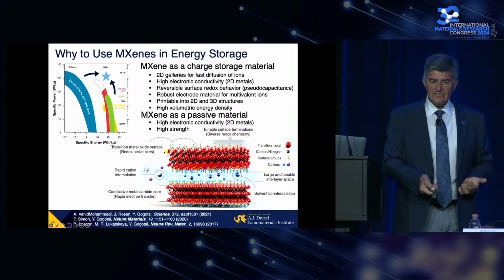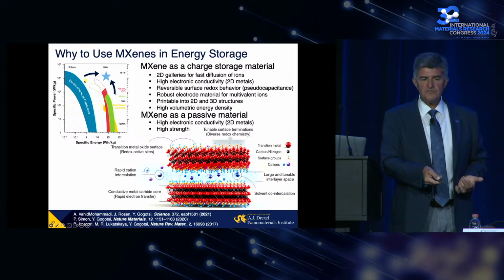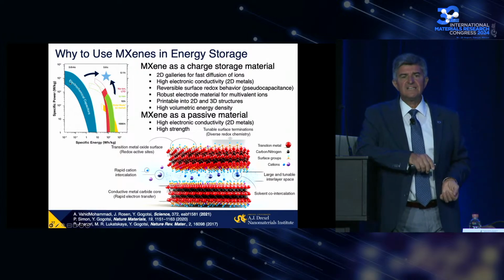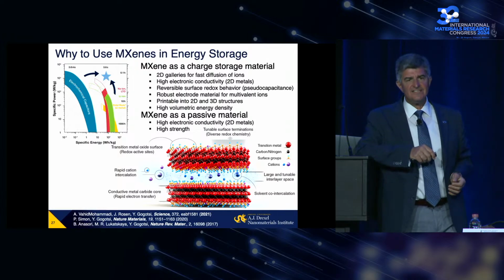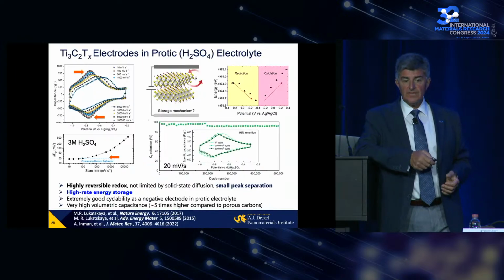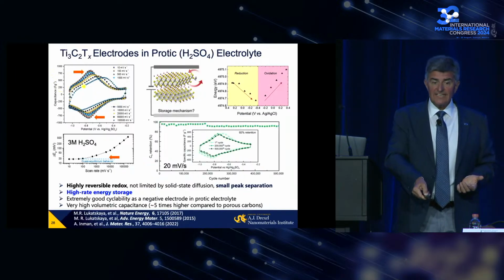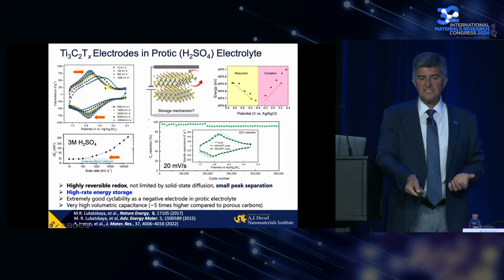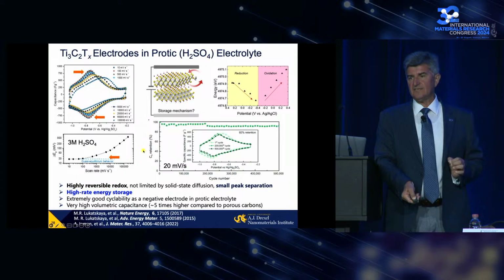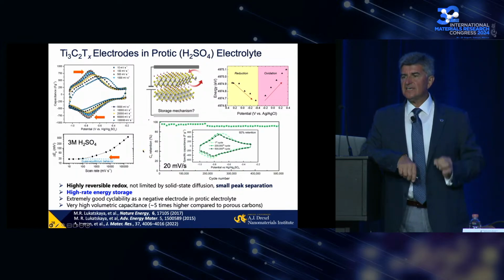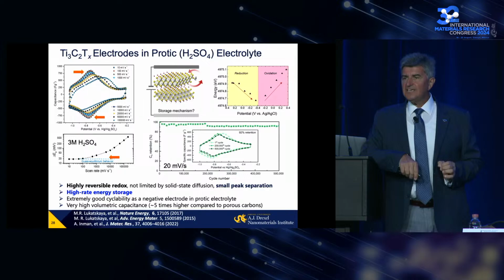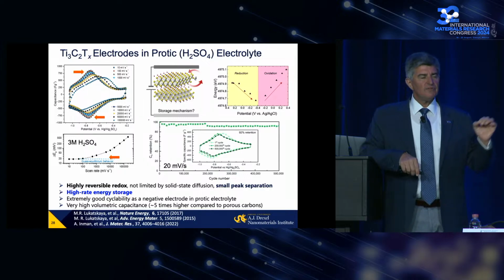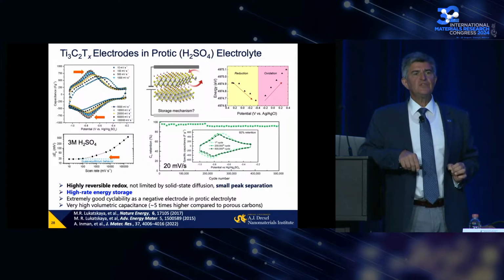And we have conductivity which is higher by 2 orders of magnitude, at least compared to activated carbon, using the fastest devices, supercapacitors here. And we showed that we can have redox energy storage. This is a cyclic voltammogram. This peak shows redox process at rates going up to 200 volts per second. So it means milliseconds charge and discharge in a protic electrolyte here.